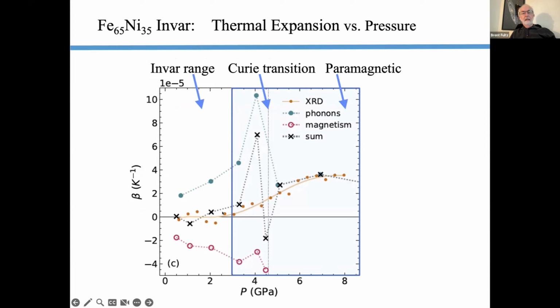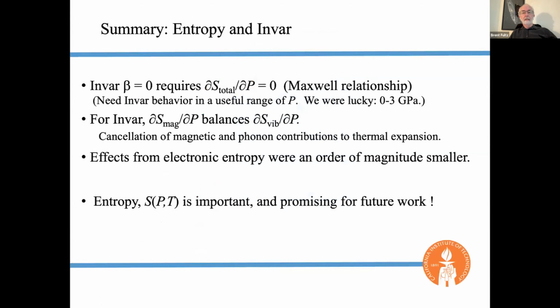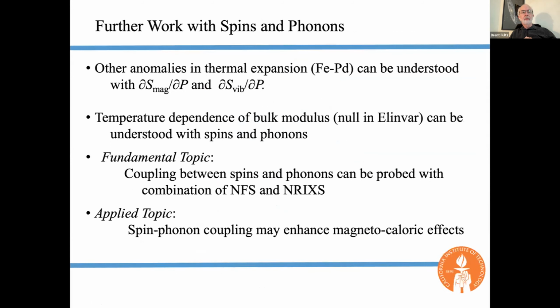And it turns out in the INVAR range below about 3 gigapascals, they don't stay constant. They're actually both increasing, which I thought was kind of unexpected. And there's some crazy behavior at the Curie transition, probably because our pressures aren't stable. Above it, we get to a normal thermal expansion. But here's the summary. We've got a delicate balance where the total entropy is 0. Magnetic balances out the vibrational part of the entropy. And this is, I think, a very promising direction for future work.